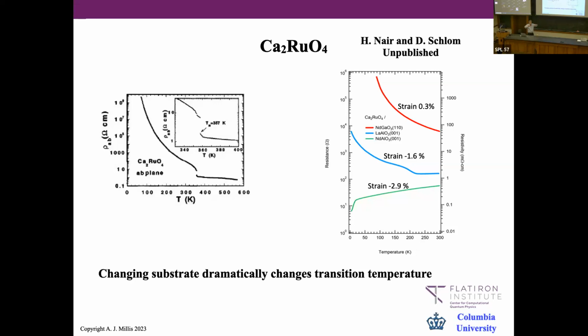For one substrate, the atomic distances in the plane are a little bigger than in the equilibrium structure. For another substrate, they're a little smaller. And you see that depending on which substrate, you can either make the transition completely go away by keeping it always metallic, or keeping it always insulating, or just move it around a little bit in temperature.